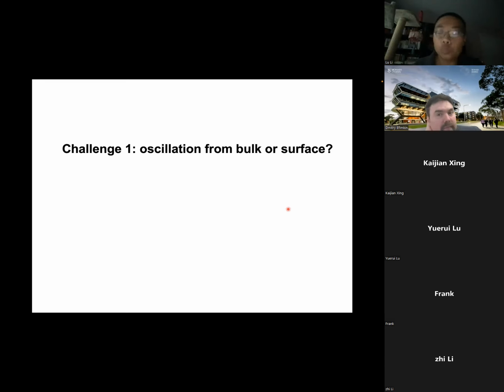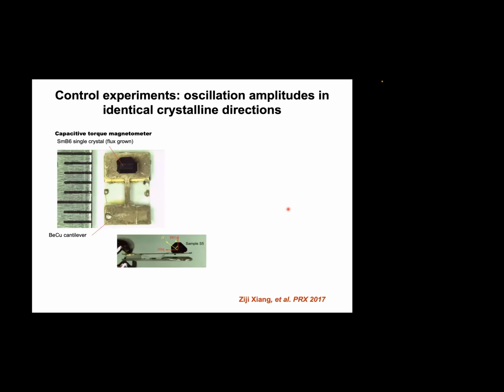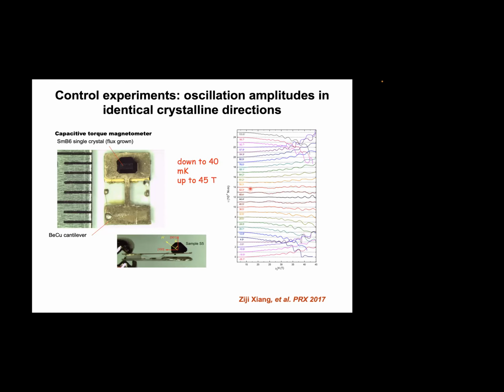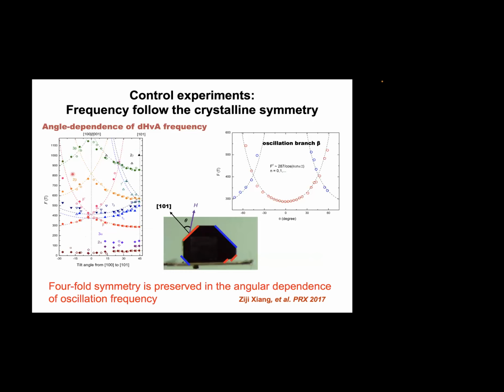That's every half a year. But what turned out is that we were able to do a control experiment by luckily finding an ugly sample that looks like this. In a regular sample, it has a shape where some facets are really large, some facets are really small, out of these 110 facets. And we confirmed oscillations down to very low temperature, and we confirmed oscillation frequencies. Just looking at this set of facets, again, there's one cosine angle dependence out of this red, one cosine angle dependence out of this blue, right? The orbital sizes follow what's expected from crystal symmetry, four-fold symmetry, because this is a cubic structure, nothing to change its electron states. Whether it's bulk or surface, the orbital sizes stay the same.